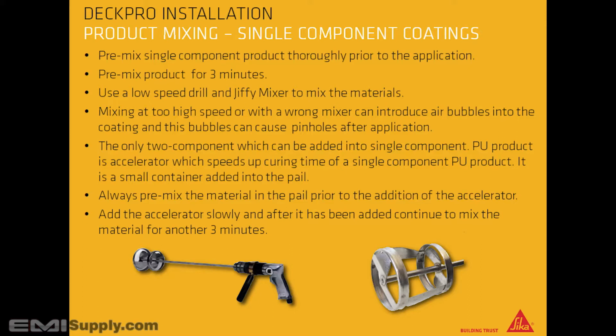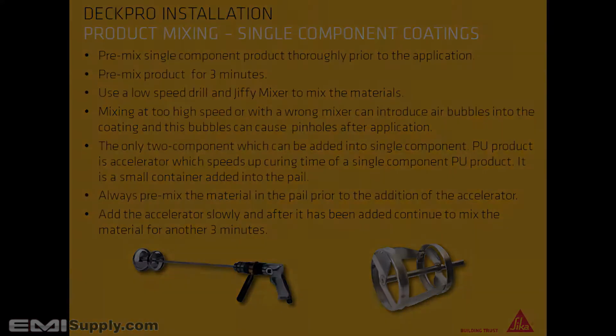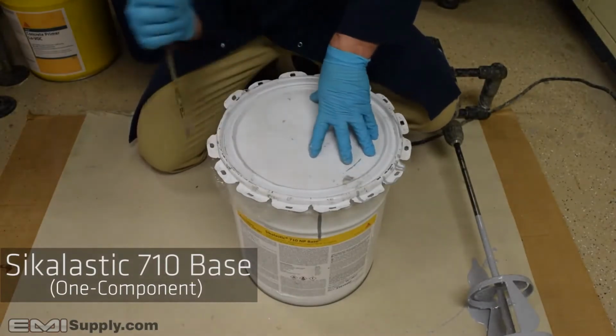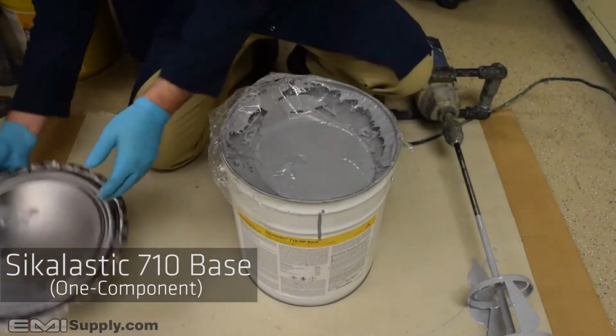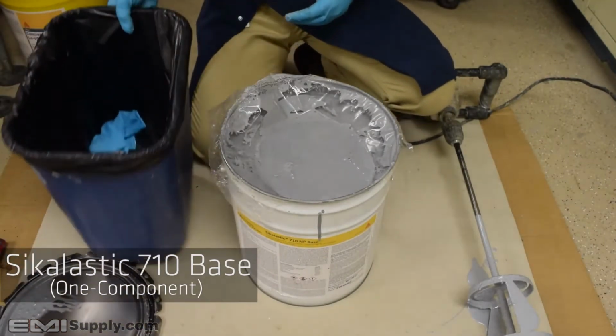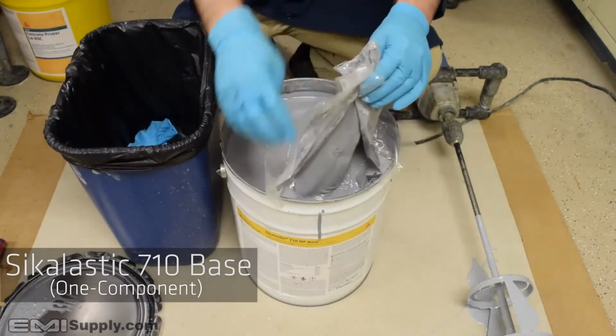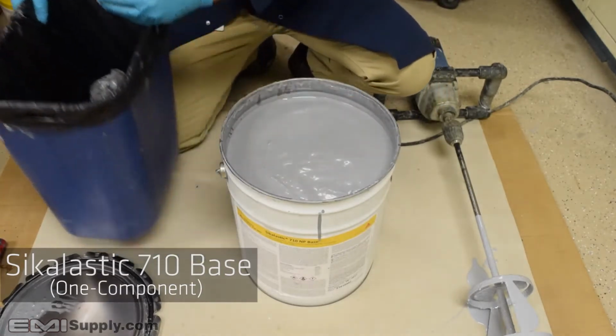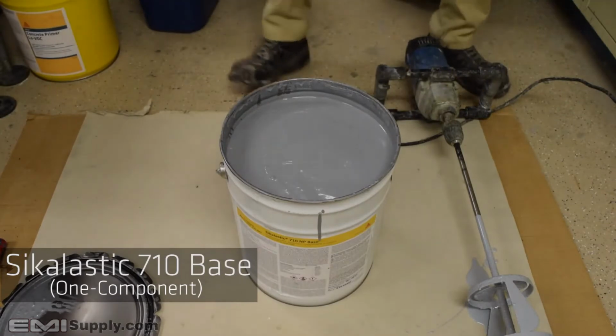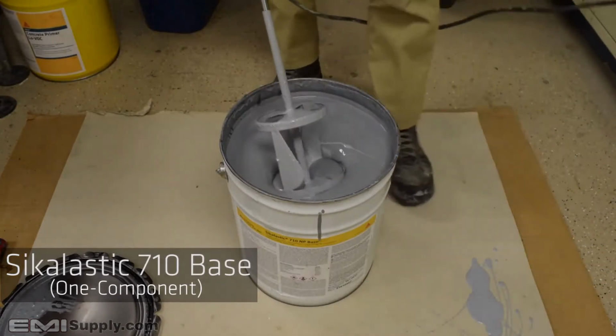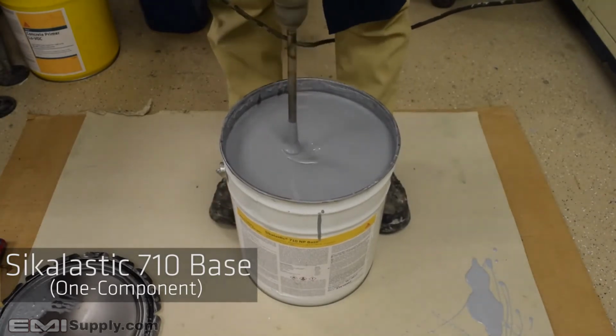The only 2-component which can be added into single-component PU product is accelerator, which speeds up curing time of a single-component PU product. It is a small container added into the pail. Always pre-mix the material in the pail prior to the addition of the accelerator. Add the accelerator slowly, and after it has been added, continue to mix the material for another 3 minutes. Begin by opening the pail of Sikalastic 710 base and removing the plastic sheet over the coating. Thoroughly mix coating at low speed until a homogeneous mixture and uniform color is obtained, typically for about 1 minute.